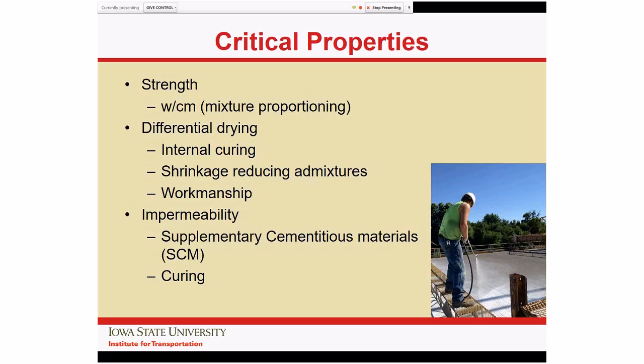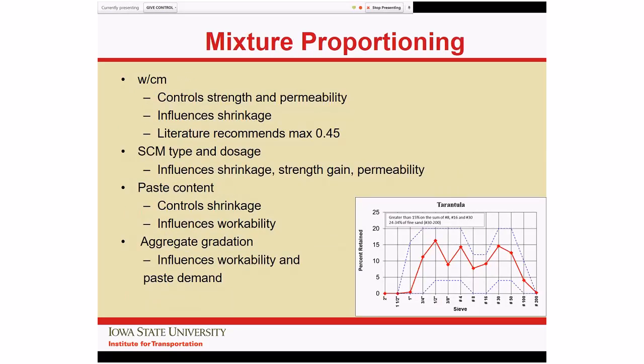The fundamentals that control permeability, again, water-cement ratio, supplementary cementing materials, and curing. And again, I'll talk about all of these in a little bit more detail in the following slides. And again, we don't lose contact with the idea that cost is fairly important. So again, just beating this a little bit harder. Water-cement ratio controls strength and permeability. The bad news is that it has a negative effect on shrinkage. The lower the water-cement ratio, particularly if you get below about 0.4, you can end up with autogenous shrinkage. And so the risk of cracking goes up if you drop your water-cement ratio too low.